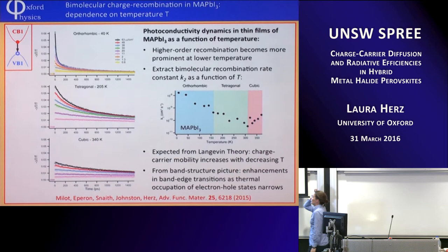When we found this we were quite shocked. What it means is that you can have a much, much higher mobility for the same amount of recombination — and the question is why. What happens with bimolecular recombination as we lower the temperature? As you go down in temperature, the bimolecular component gets faster and faster; k₂ goes up by two orders of magnitude from room temperature to near zero Kelvin. One way to understand this is that as you cool the system, the thermal occupation near the band edge gets narrower and narrower because it's no longer thermally smeared, giving better overlap and better recombination — similar to what's seen in gallium arsenide.